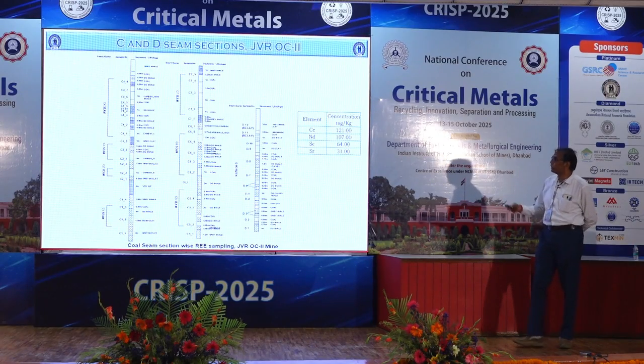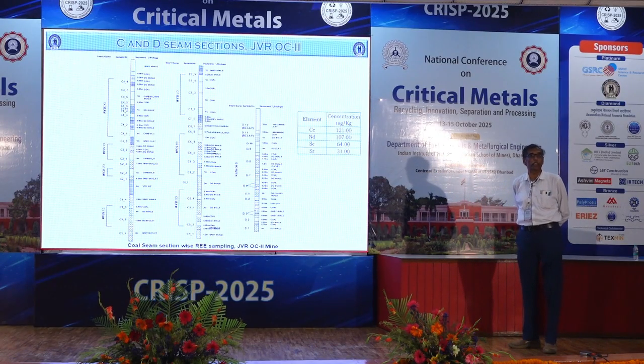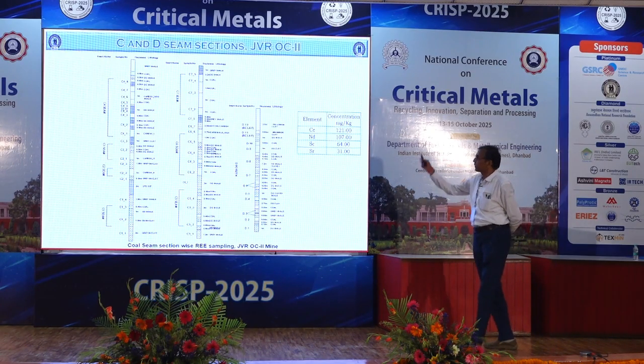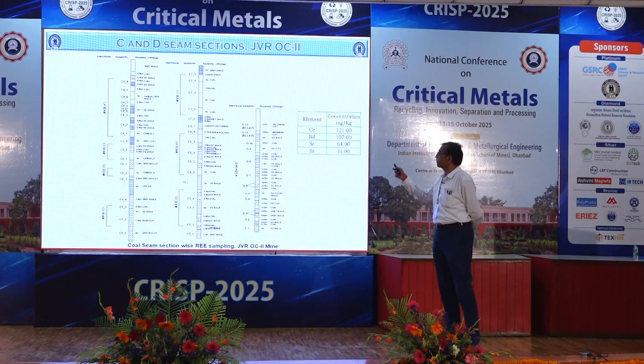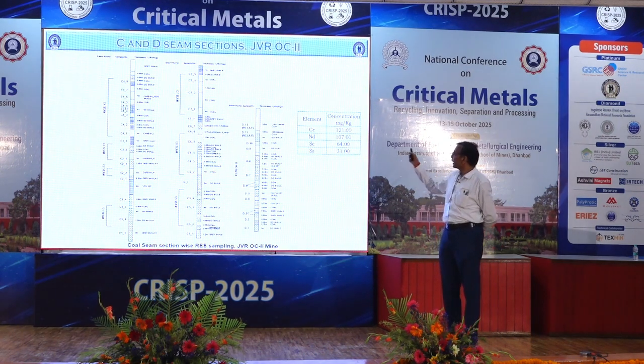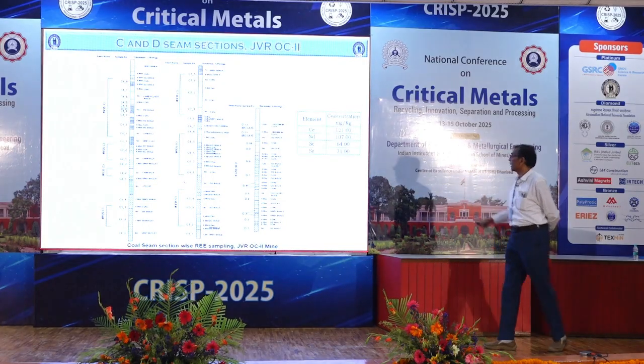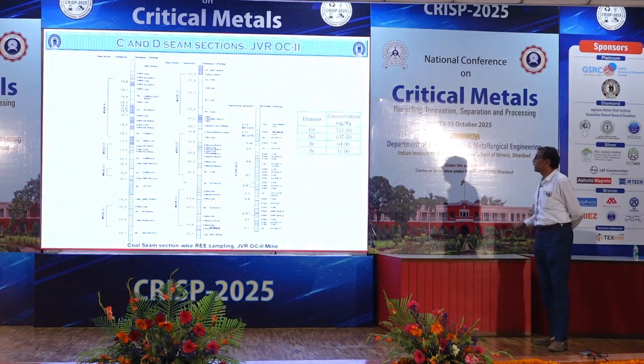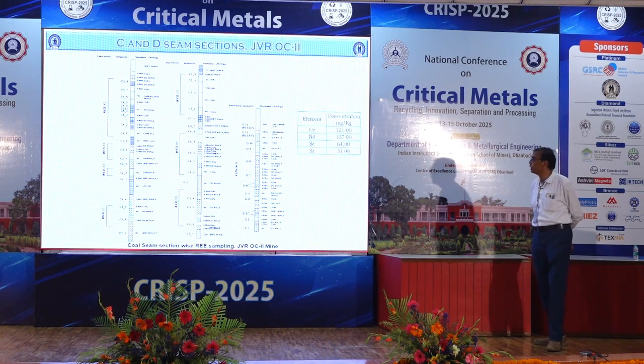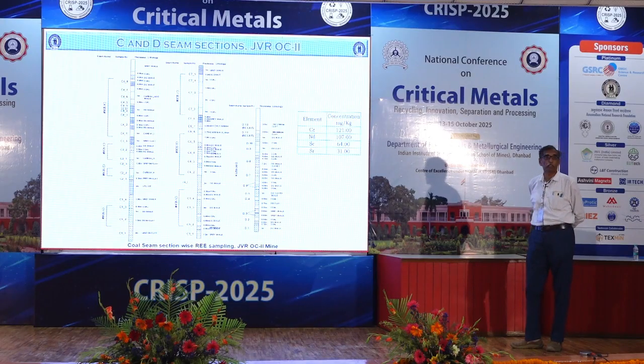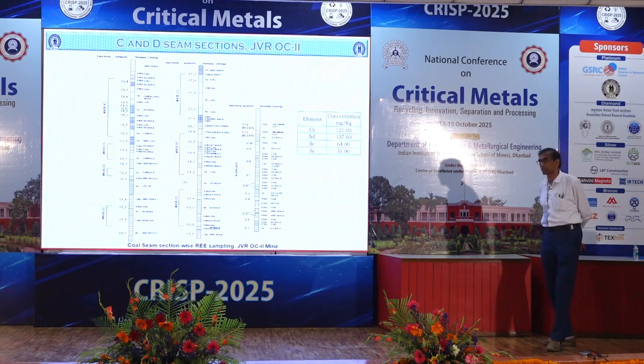This is the closer look. Generally, geologists call them seam structures on 1:50 scale. Meticulously we collected the samples within the area. For every meter, and wherever a lithological change is there, we collected a sample. In those samples we got these values. You can see neodymium and praseodymium together 150. Praseodymium has not been written here. Scandium and strontium together more than 100. Dysprosium and terbium more than 30 ppm.